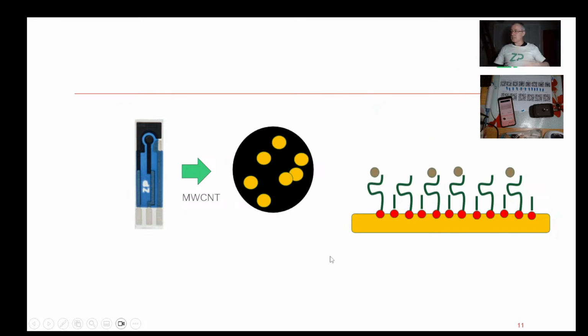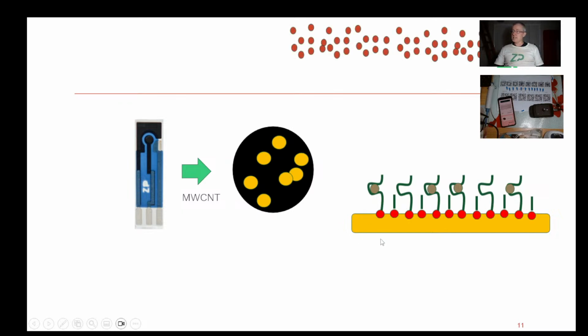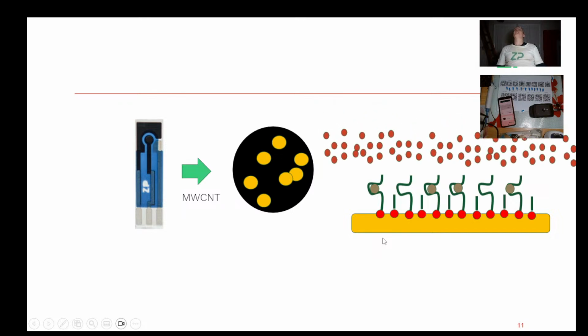Then what they're doing is actually doing that assay. Once they've got their surface functionalized, and I'll describe that, then they're doing the assay itself by adding PSA, and they're reading that binding using a sort of Faradaic EIS type reading, where they're using something like ferrocyanide, which wants to oxidize on the surface, but depending on the amount of blocking, or binding, I should say, between the aptamer and the PSA, then the signal changes according to it. So it's basically a blocking assay.